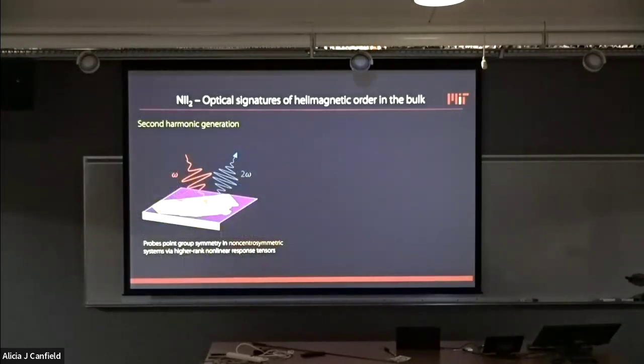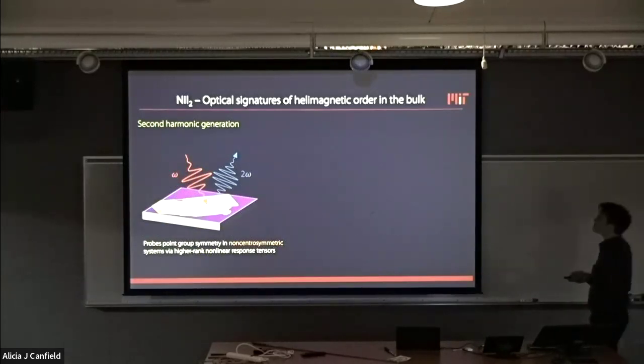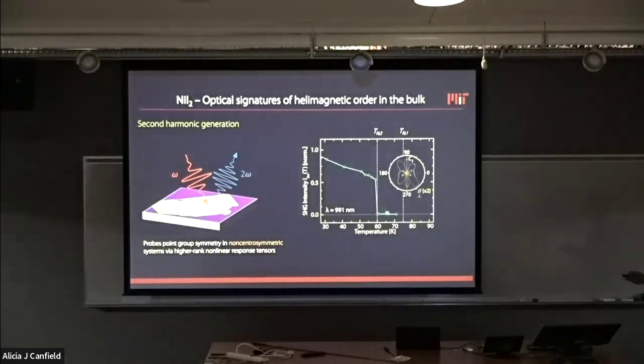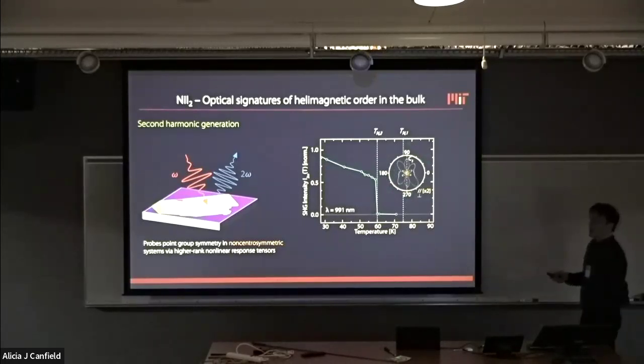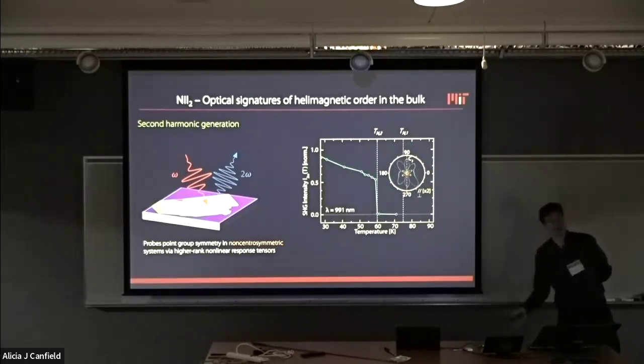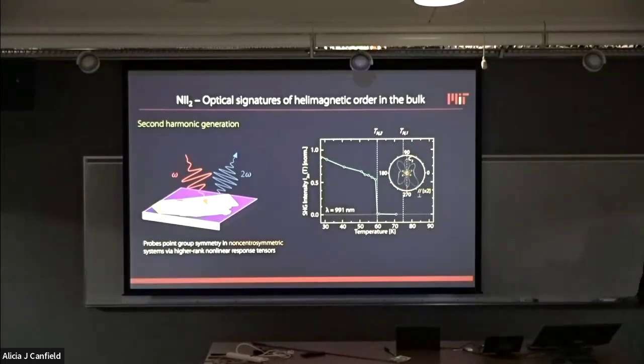Then we look with SHG, second harmonic generation, which is a probe of breaking of inversion symmetry. And second harmonic generation again shows a sudden jump at 59 Kelvin, showing very cleanly this transition. If you look at the rotational anisotropy patterns, you can confirm that the low temperature point group will be C2, so it really has only one symmetry axis.